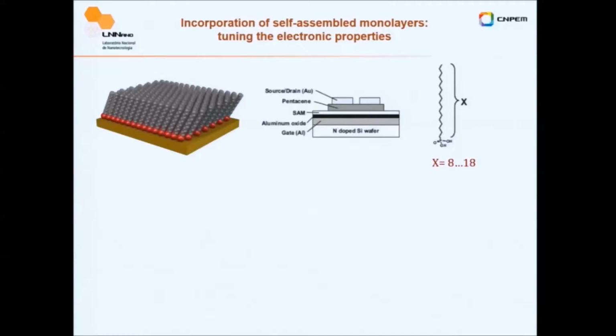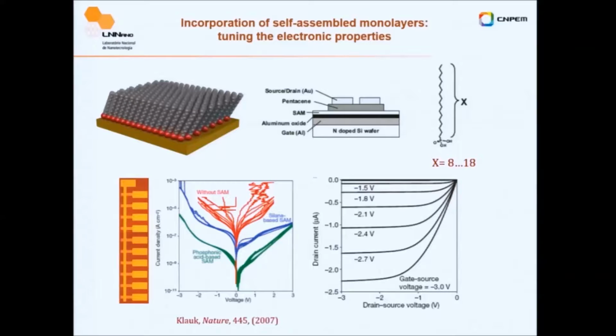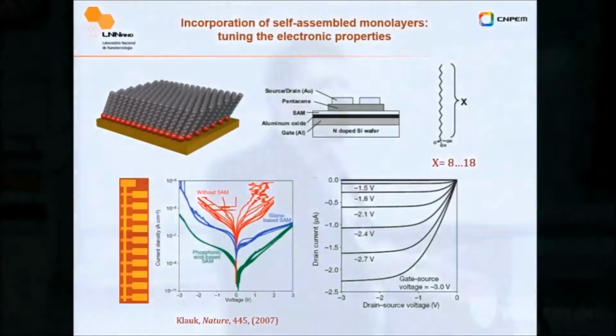One other phase of this project was, okay, how can I get tunability? How can I change the material? This comes from some solutions presented a few years ago by Hagen Klauk and his group on organic transistors, where they managed to drop the operation voltage to a few volts by simply adding a self-assembled monolayer on top of the aluminum oxide layer. And the main output was this: they brought the voltage from 30 volts to 3 volts.